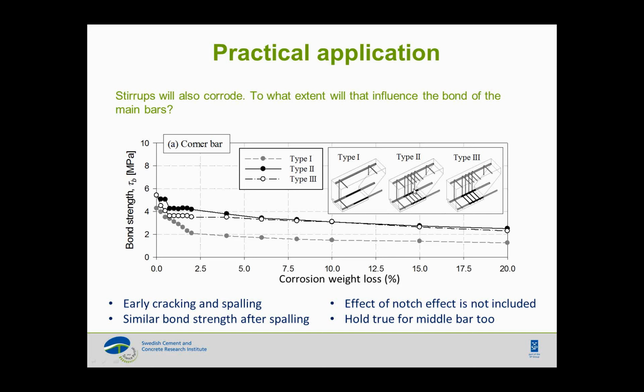But in the case where we have stirrups included, then we start from a higher point. The difference between type 2 and type 3 is that in type 3 we also have the stirrups corroding. And what happens is that in that case you have a sharp drop in the beginning and then continue. But if you do not have any corrosion on the stirrups, then you maintain a little bit higher bond strength for low corrosion penetration. That means that the impact of your stirrups being exposed to corrosion is that you get a lot earlier cracking and maybe earlier spalling, but the very final capacity is not influenced by the corrosion of stirrups if you do not get yielding in stirrups. So this is another practical application of the model we've developed.